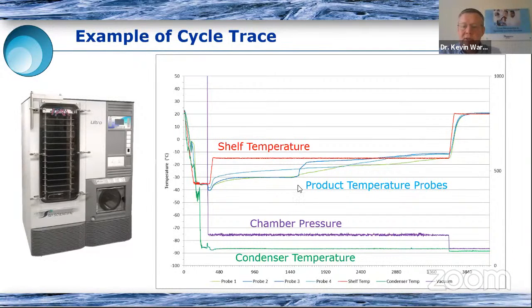We're also interested in what's happening to the product, and this is where our collapse or micro collapse or eutectic temperature can come into play, because what we're ultimately interested in is what is happening to the product when we use these freeze drying conditions. And so we can classically use thermocouples or resistance thermometers in our freeze dryer in sample containers of our formulation to see what it's experiencing in terms of its time temperature profile. And so if we have a collapse temperature of -20, you can see that in primary drying, all of these product temperature probes are below -20 until they reach the point where they start to rise partway through primary drying, indicating that those samples are becoming dry. And this is how we use the information.